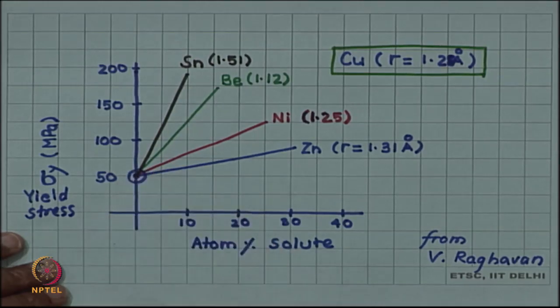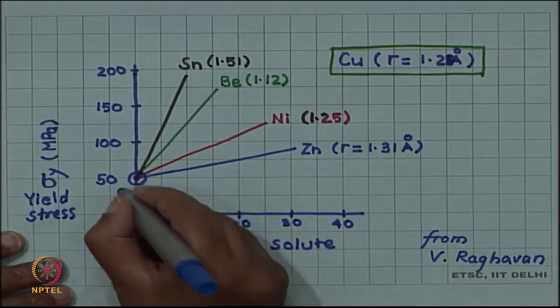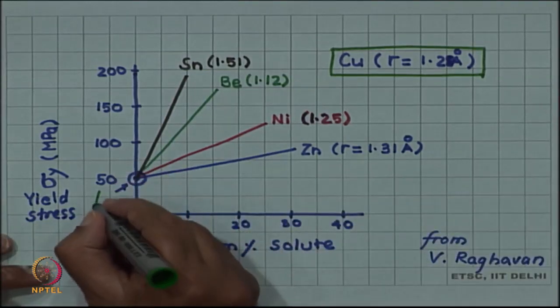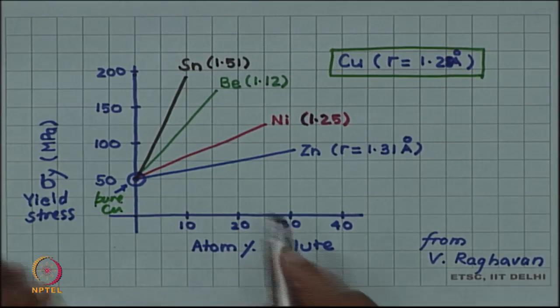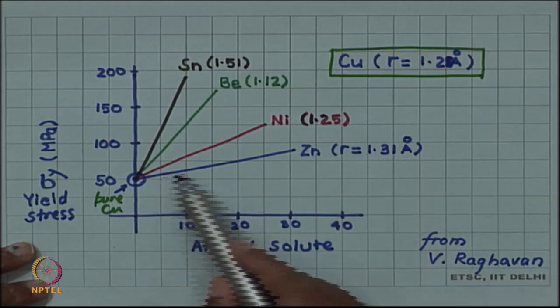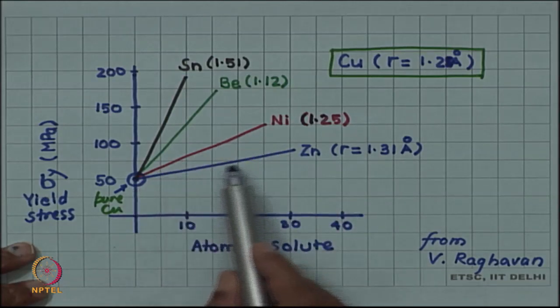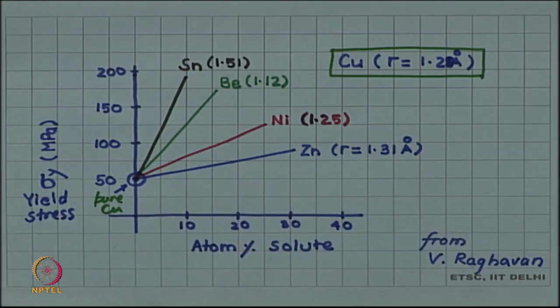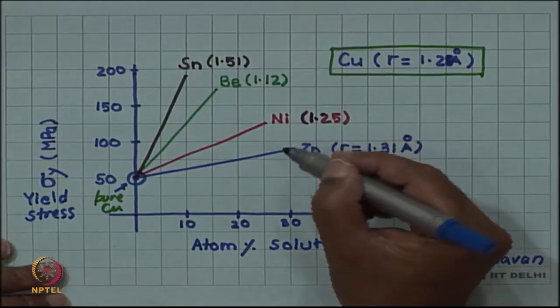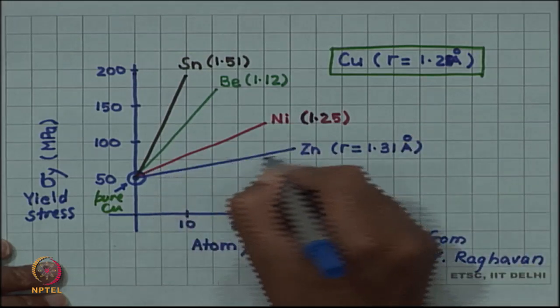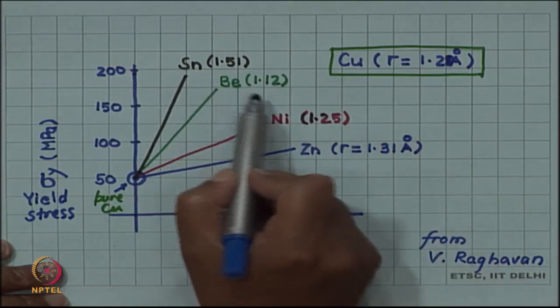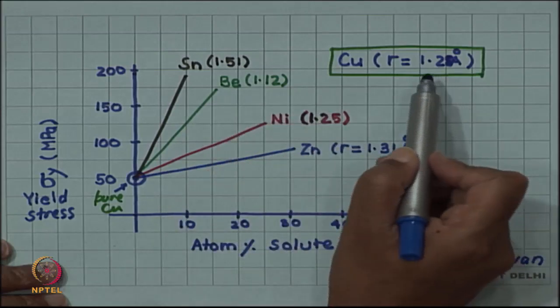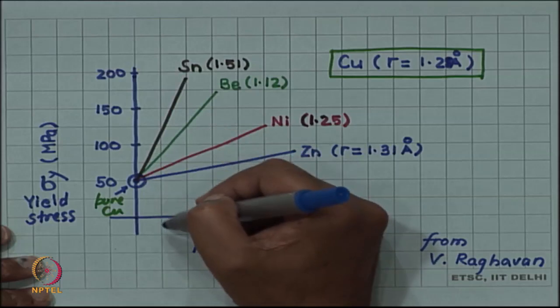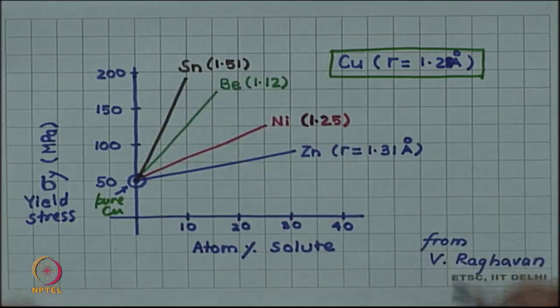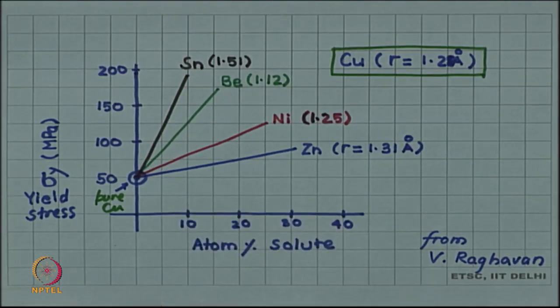This 50 megapascal is for the pure copper because 0% solute. So, this is for pure copper. And as you add the solute, a strengthening is taking place. So, whatever solute you add, with the increasing amount of solute, strength increases. However, if the radius ratio is small, the effect is small, the slope is small, whereas if radius difference is large, as in the case of tin and beryllium, the difference is more with the base element copper. So, for a small amount of solute, the hardening is much more. So, you can see how the solid solution hardening depends both on the size difference as well as the amount of solute.